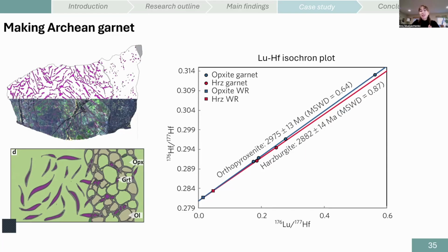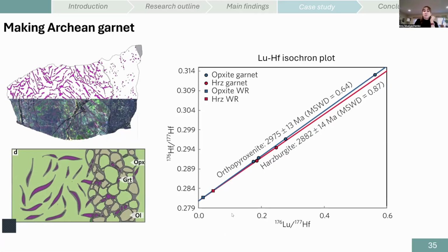Despite this, we obtained robust lutetium-hafnium ages for both parts of the sample, showing that indeed the exsolved part is at least 100 million years older than the fine-grained recrystallized part. So these results proved our initial idea that this part is a product of recrystallization of the exsolved lamellar part and allowed me to reconstruct a sequence of events explaining, or trying to explain, how this composite rock formed.